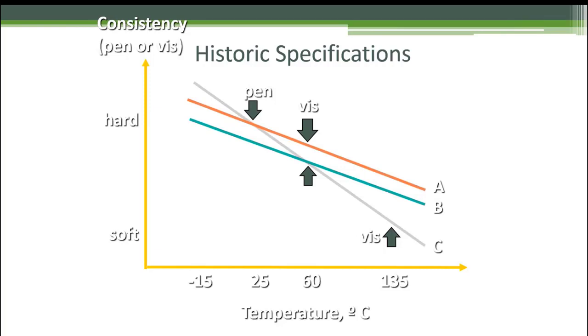Okay, kind of finishing off this on the asphalt side and then leaving a little time for questions, is we need to get into the paving grade asphalts. So we talked about penetration grade, shortened to pen here, viscosity graded, VIS here. So if you remember, our penetration test is run at 77 degrees Fahrenheit, which is 25 degrees centigrade. So if we had spec'd a pen graded asphalt meeting a certain range, 85 to 100 say, both A and C in this diagram would meet the requirement of our specification, right?